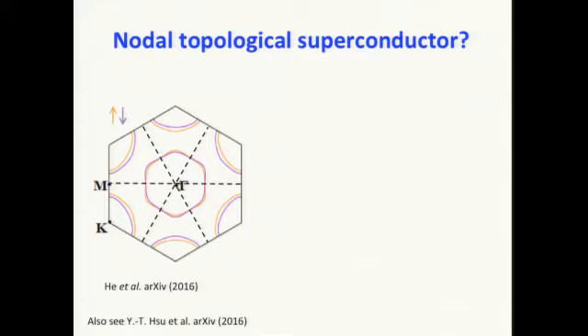The CDW order is quite decoupled from the superconducting order. The CDW gaps only open up at a few points at the K pocket and the K prime. So if there is the charge density wave order, or if there isn't in your system, you would anyway observe this. It's completely decoupled, so you can also not take it into account in your theory, and the spin-orbit interaction picture should still be there. So I think the picture should be more or less correct here.